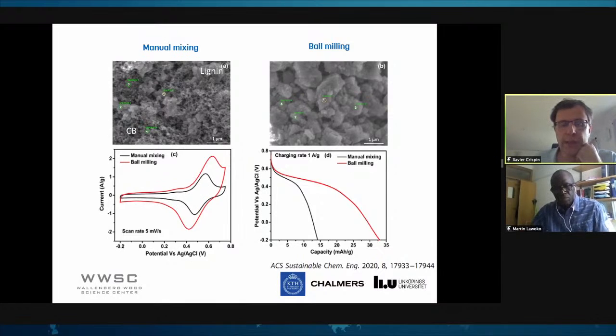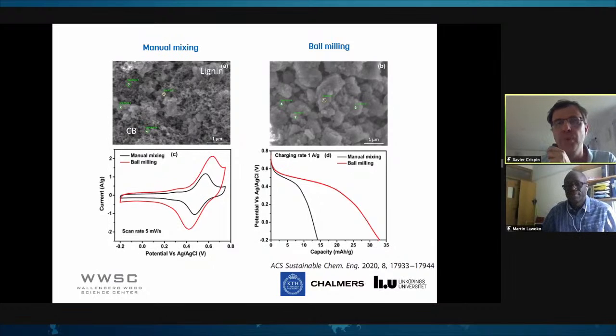Yeah, definitely. This is just, let's say, not using the smart tool of chemistry. We are just using ball milling. But there are many more exciting tracks, I think, that could be used both on the lignin side and on the carbon side. For instance, nanographite can be to some extent dispersed in a very strong basic media. Lignin can also be dissolved in basic media. So you can probably bring them together, and we have done some attempts, but we have not worked enough on that. But this could be a way to bring them intimately together without having to use the big hammer of ball milling.